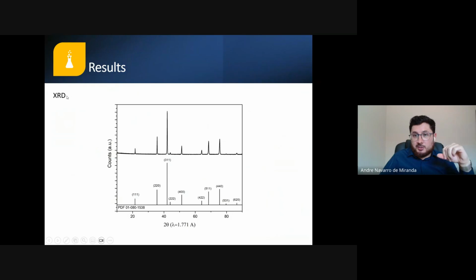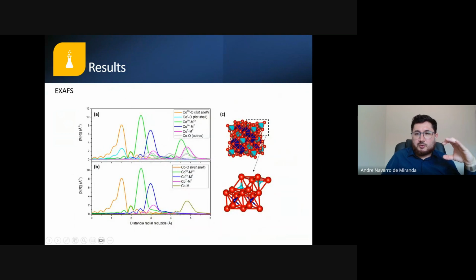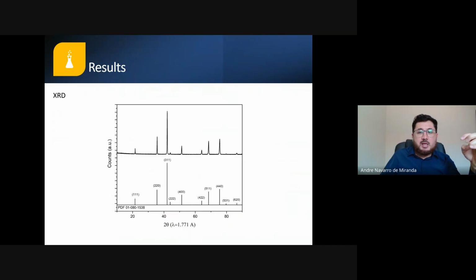Yes, so this is X-ray diffraction. Each plane here is a plane of this cobalt structure. For example, this could be 111, this could be 311, this could be 011. I'm not sure if you are familiar with the technique. Each plane here is one plane for the cobalt oxide spinel. And then here is the experimental result. Here is a pattern that you have in the literature, a PDF as we call it, which shows the position and the height of the peaks. Then we compare it with the experimental results, and we could see that we have a really crystalline phase, not amorphous, in the spinel phase. It's not another phase.